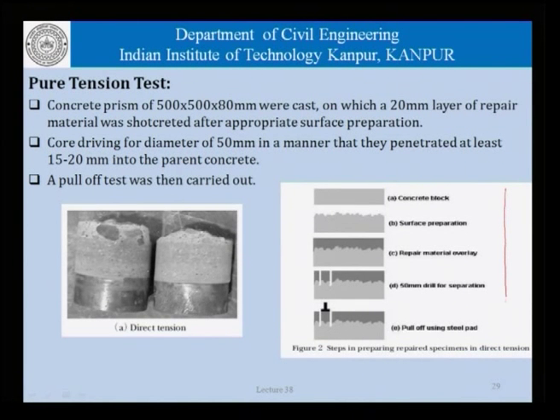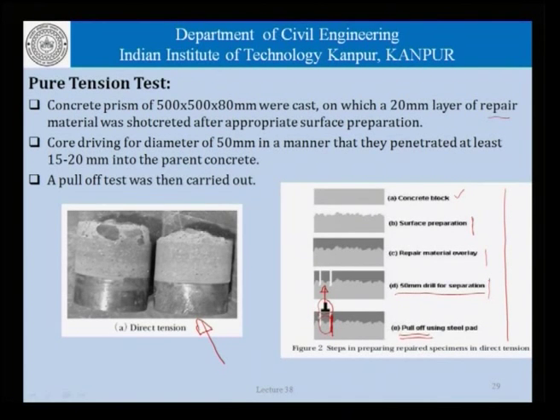For the pure tension test, this outlines the basic process: casting the concrete block of 500 by 500 by 80, on which a layer of 20 mm of repair material is to be placed. The surface preparation is carried out, repair material is overlaid, and a drill is used to create a specimen which is shown here, and then we carry out a pull-off test. A pull-off test really means fixing a fixture on the surface and trying to pull it off, thereby ensuring failure in this small neighborhood, whether the failure occurs within the repair material, at the interface, or in the concrete. So, in order to do that, the depth that we make as far as the coring is concerned is fairly important, and this here shows a failed specimen.